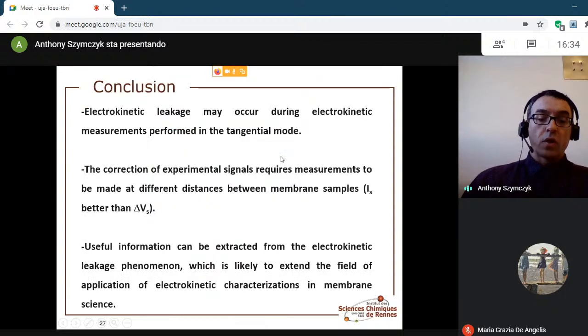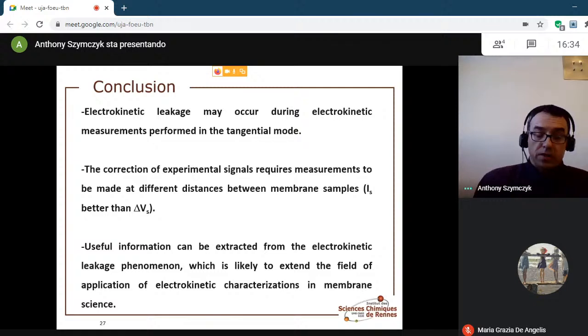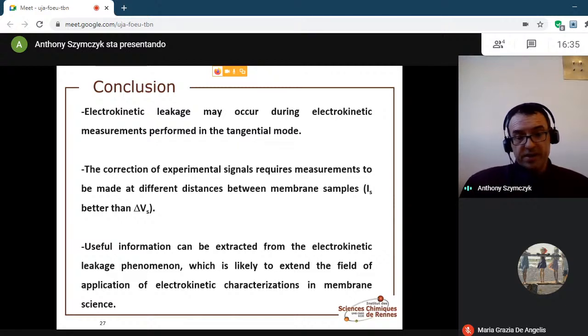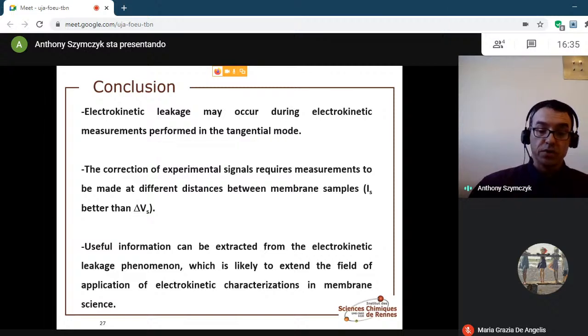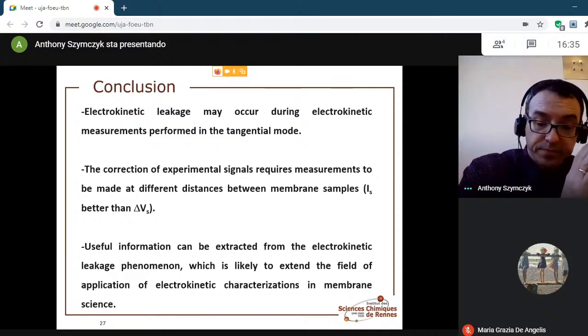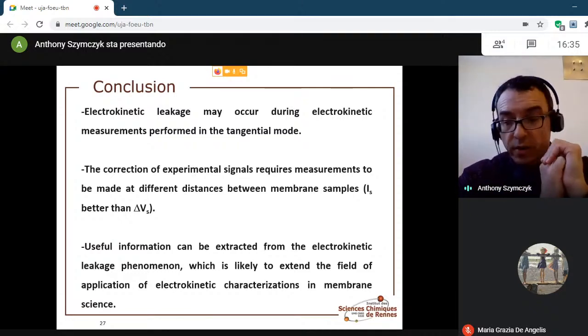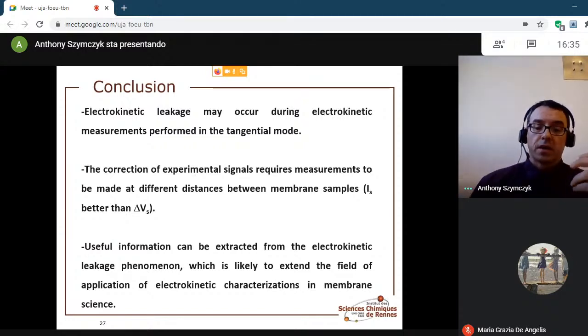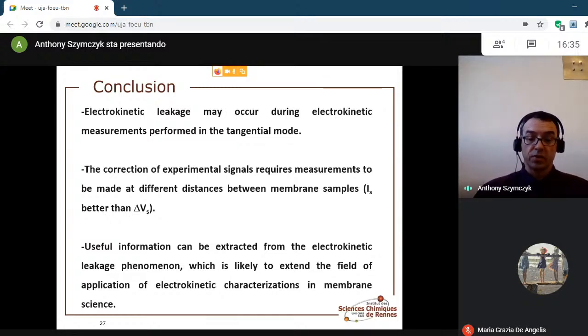To conclude, this webinar focused on the electrokinetic leakage phenomenon that can interfere in electrokinetic measurements performed in tangential mode, which is nowadays the most commonly used measurement mode for membrane characterization. We have seen that this parasitic phenomenon can lead to incorrect interpretation of electrokinetic measurements, in particular to inaccurate values of the zeta potential and also errors in the estimation of the isoelectric point of membranes. We've seen how to take this electrokinetic leakage phenomenon into account and how to correct the experimental measurements in order to get an accurate zeta potential determination.